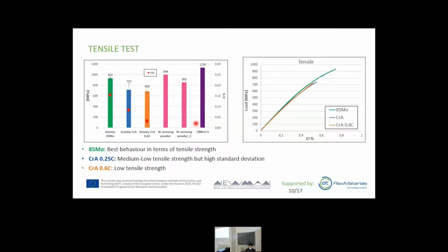Moving to the mechanical characterization and in particular to the tensile test, the 85MO shows the best behavior in terms of tensile strength. And then we have the CRA with 0.25% of carbon with a medium tensile strength, but with a high standard deviation of the results. And finally, we have the CRA with 0.6% of carbon. If we compare the results of the 85MO with other two powders containing nickel, we see that the results are similar, while if we compare the same powder, the 85MO, with the results of a forged steel, we are about 200 megapascal lower due to the different